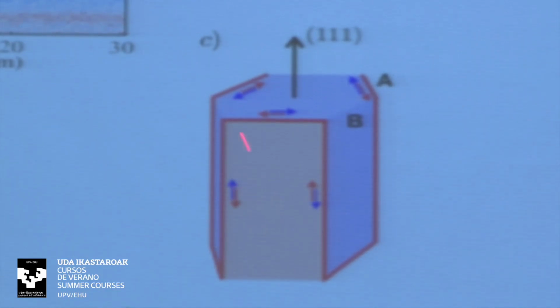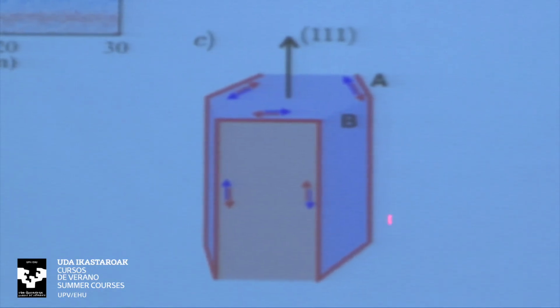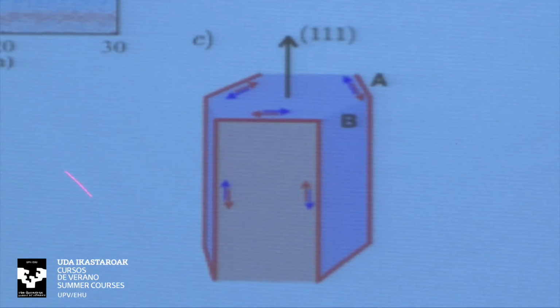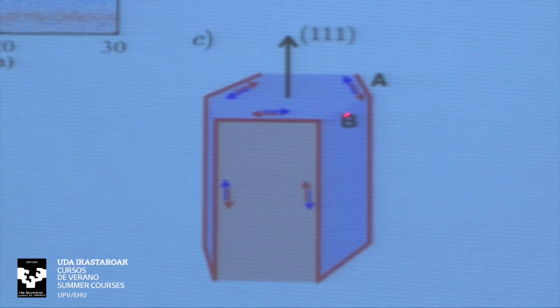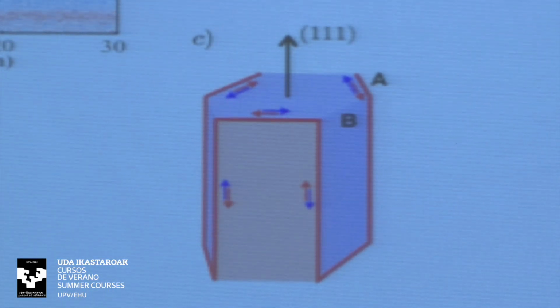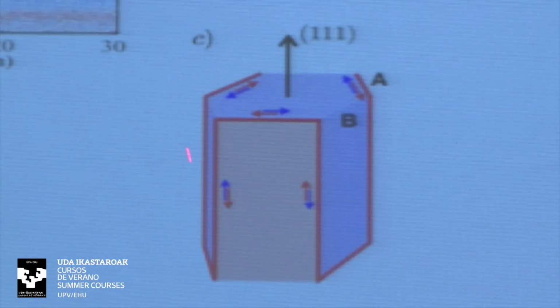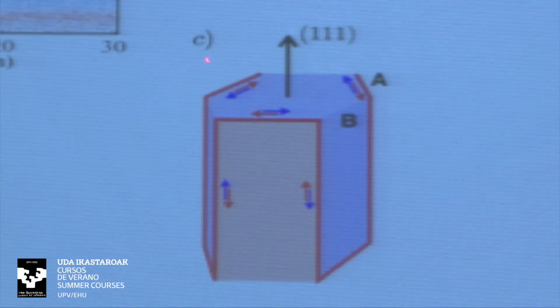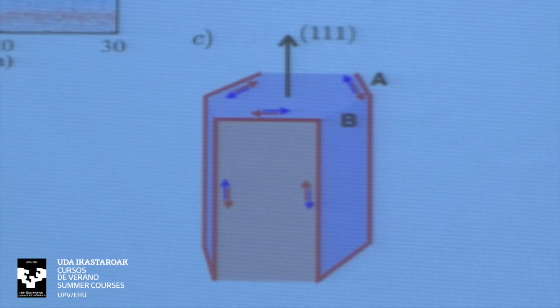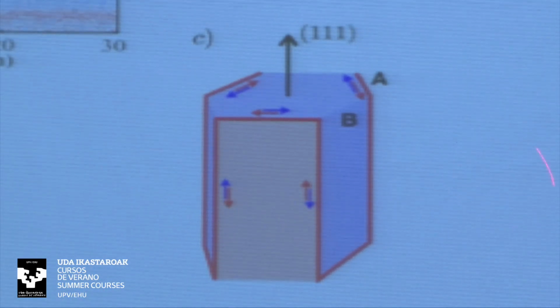Basically, because these different surfaces have different inversion eigenvalues, you expect to bind helical modes at these interfaces between the different facets. This is a possible explanation for the helical mode that is observed. So it serpentines along these edges of this nanowire-like shape that is calculated here.